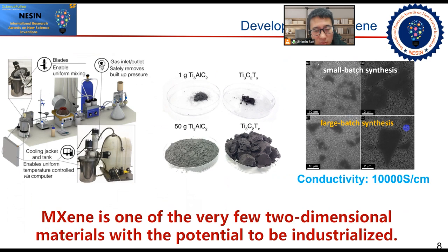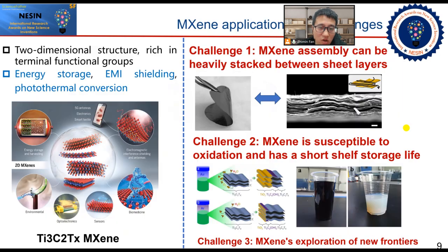Importantly, by scaling up the production of MXene in 2020, Gogotsi found that the properties of MXene prepared in bulk are almost indistinguishable from those of laboratory grade, which creates a significant difference from graphene. Therefore, MXene is one of the very few two-dimensional materials that have the potential to be industrialized. Of course, there are more than 20 types of MXene, and its diversity makes it show a wide range of